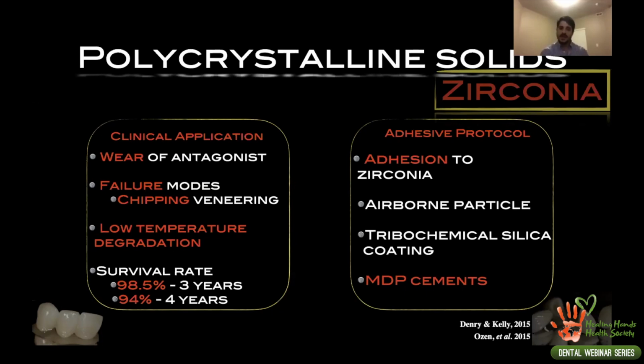And again, when we look at the failure modes, the most common failure mode with zirconia in the literature is chipping of the veneering porcelain. But now that we have a monolithic restoration, there is no veneering porcelain chipping.